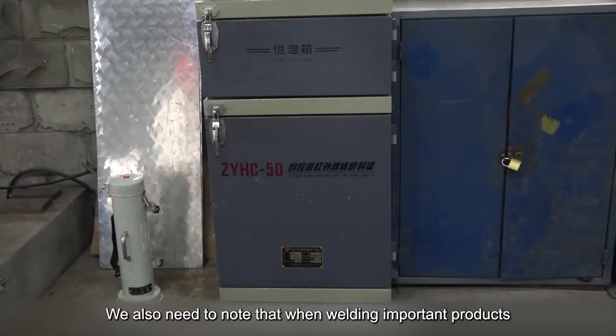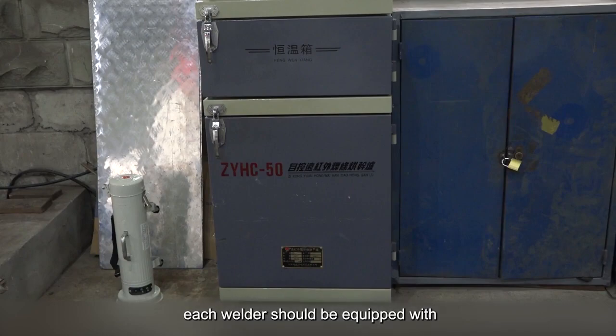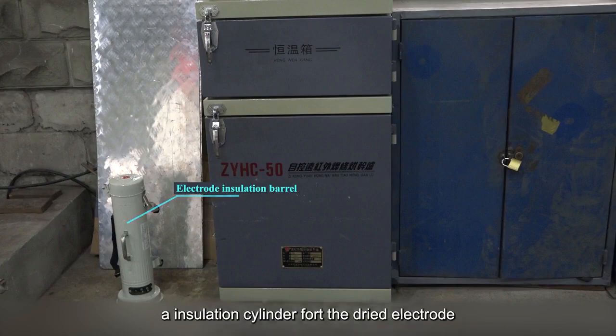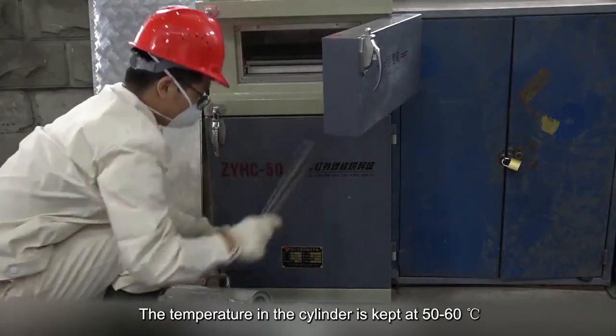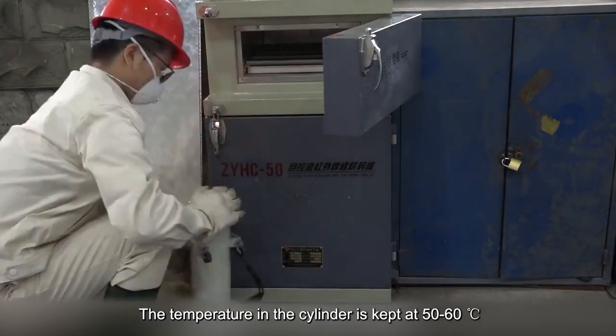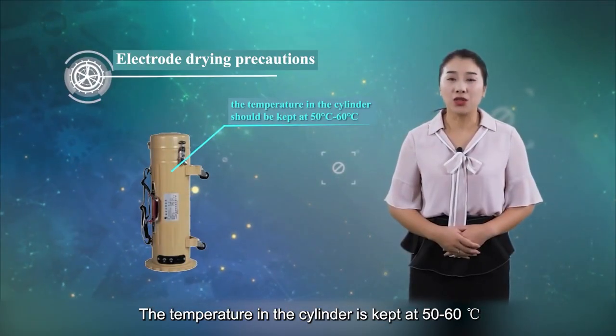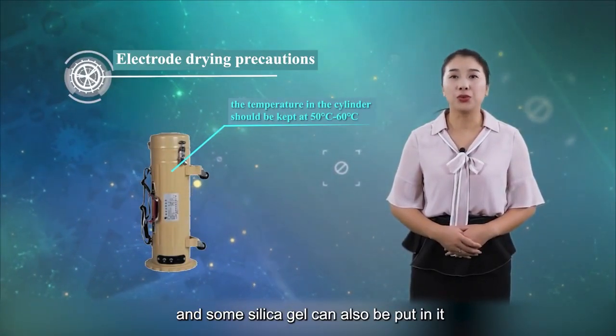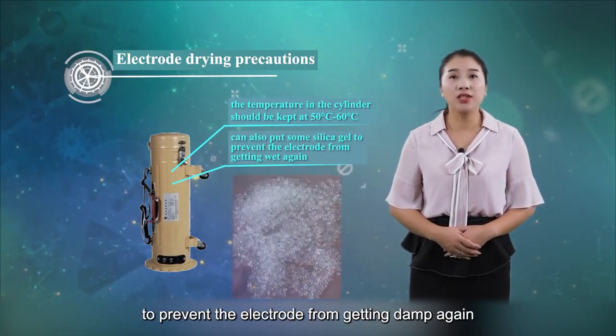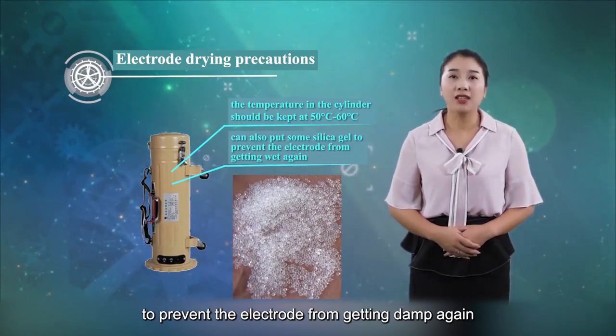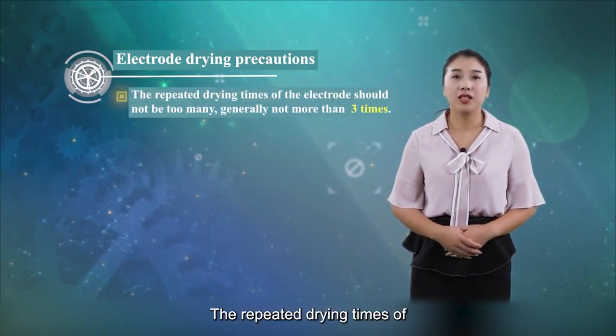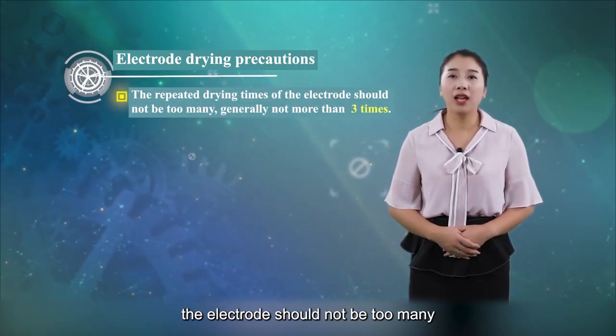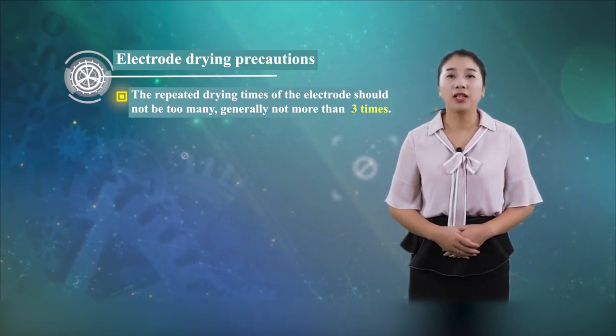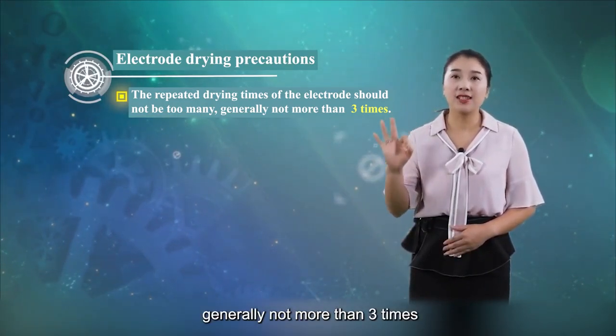We also need to note that when welding important products, each welder should be equipped with an insulation cylinder for the dried electrode. The temperature in the cylinder is kept at 50 to 60 degrees, and some silica gel can also be put in to prevent an electrode from getting damp again. The repeated drying times of an electrode should not be too many, generally not more than 3 times.